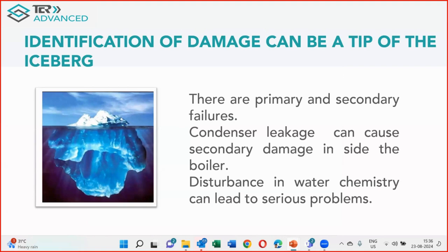There are primary and secondary failures. It is very important that when you do RLA of your boilers, we sometimes ignore condensers, because when you have problems in the water wall tubes, the condenser leakages are responsible for the water wall damages. So when you do RLA of the boilers, it is important to understand the past failures and do the testing. I recommend many times that whatever your time constraint, the best way to identify condenser leakages is through helium leak test. Helium leak tests are the gold standard,